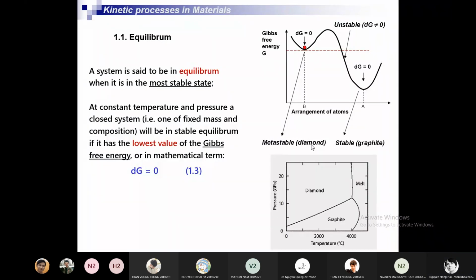So you see the pressure and temperature diagram of carbon. Here graphite can exist at this temperature and relatively low pressure. Diamond exists at a similar temperature to graphite, but the pressure is much higher. See the three states, three forms of carbon: graphite, diamond, and liquid at very high temperature, more than 4,000 degrees Celsius.